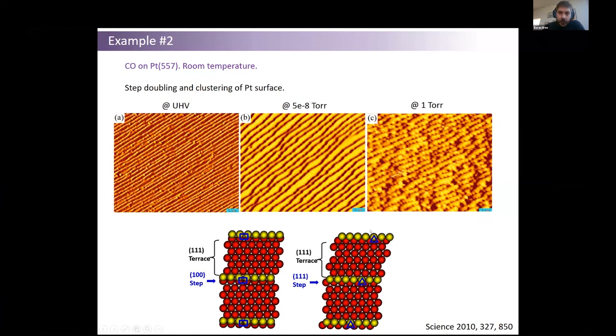And what I don't show here is that there is another surface, the platinum 332 surface, that's basically very similar to this platinum 557 surface. Again, you have a platinum 111 surface, and again, there is a miscut of 10 degrees. But this miscut is now in another direction, and instead of these microfacets or steps of 100 type, you have 111 type of steps. Interestingly enough, at low pressures, there was no step doubling for the platinum 332 surface, and at higher pressures, there was clustering, but the clustering was in the form of parallelograms.